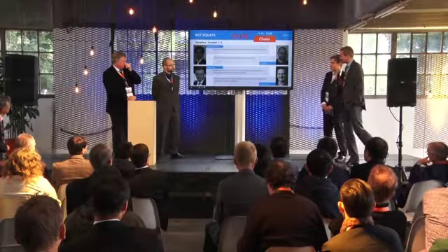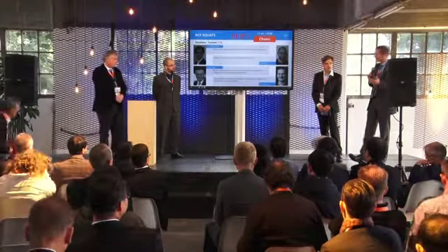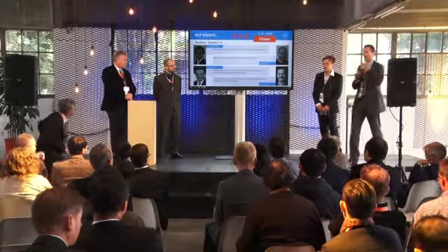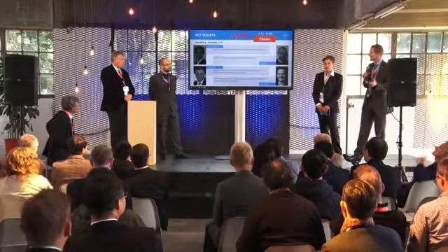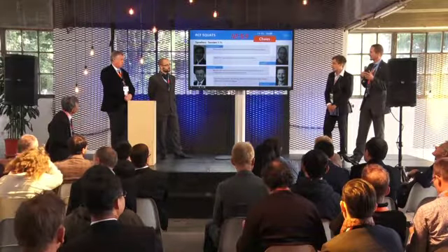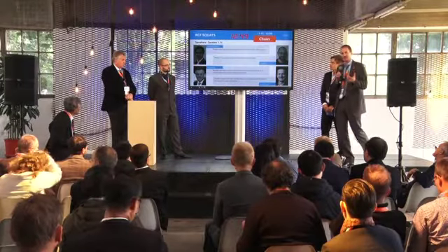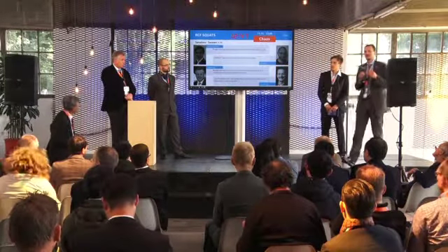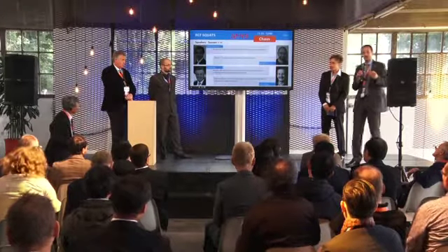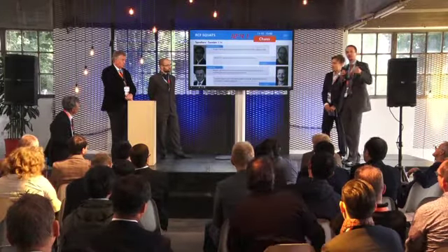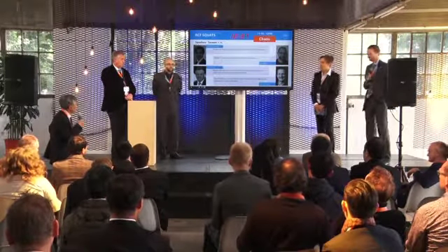So for us it was very important to show that with rail milling you can contribute to squat mitigation, being capable of removing even deep defects, adjust the profile accordingly, and do this in a way that you remove all initiation points but also do not introduce any new initiation points. However, very important to highlight, it is a contribution to mitigation but not a solution to the problem.